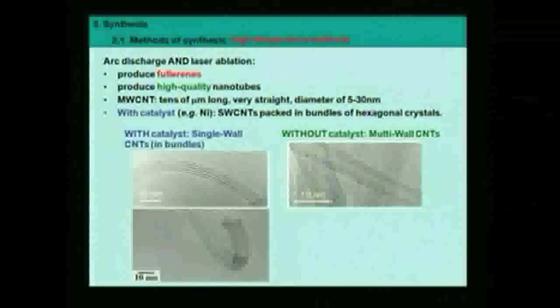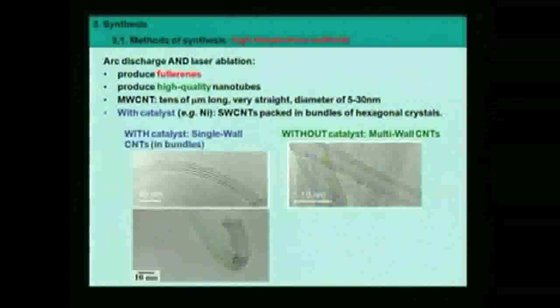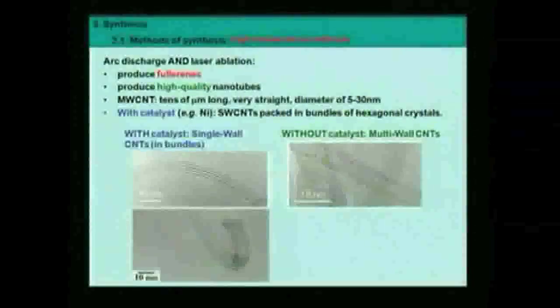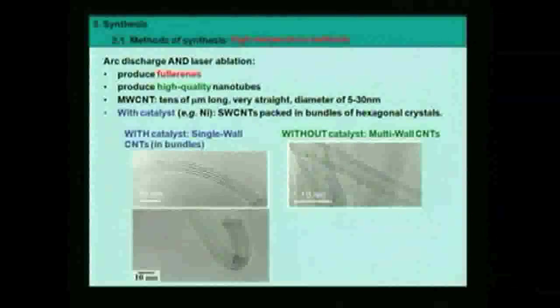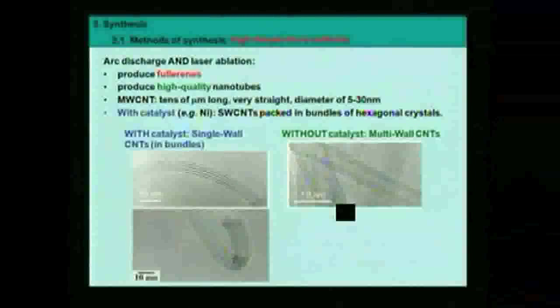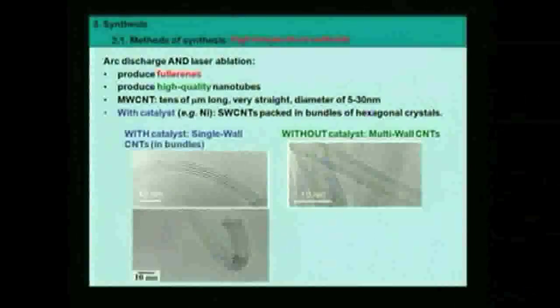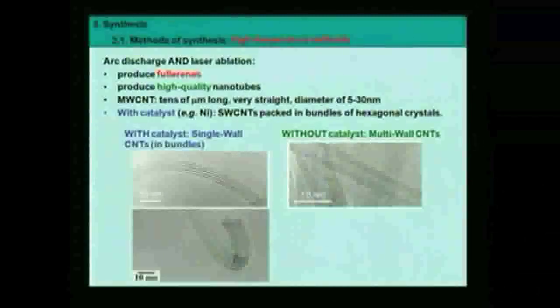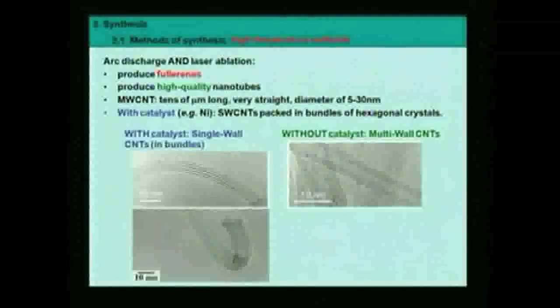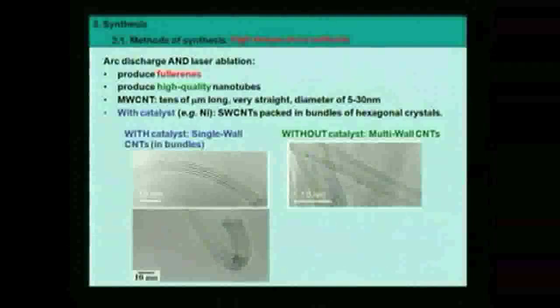Yesterday we said that to obtain a well crystalline material, we needed to give atoms time and energy to go to the most stable position. Here we have a lot of energy because we work at very high temperatures. It means that the carbon structures, even if they do not form the most stable structure at first, due to the thermal energy, they will rearrange, restructure very quickly and go to the most stable state, the most stable structure, which is without defects. Okay? So this is why we have so few defects in these structures, because we work at high temperature.